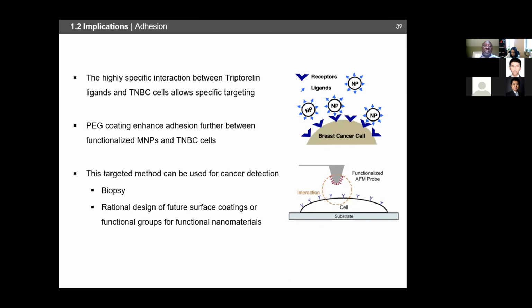Now, this has major implications because it means, of course, that we can use these specific interactions to enable specific targeting. And we can also use a combination of these LHRH and PEG to really enrich the entry of the nanoparticles into cancer cells. But ultimately, with the methods that we have, this can become a method that's used for analyzing biopsies and perhaps developing coatings of functional groups for cell targeting.